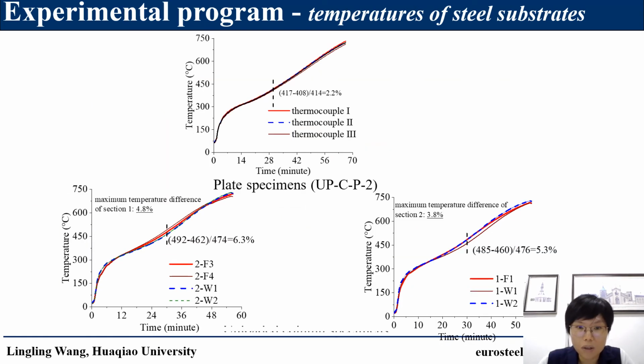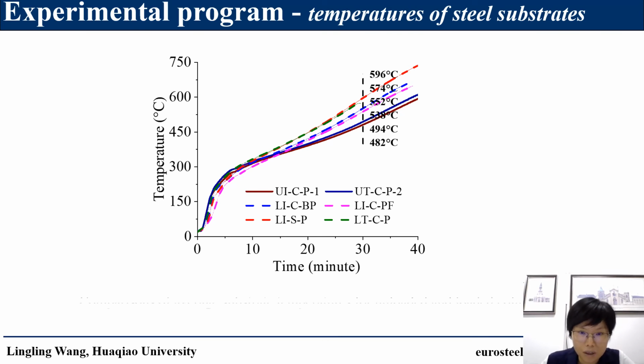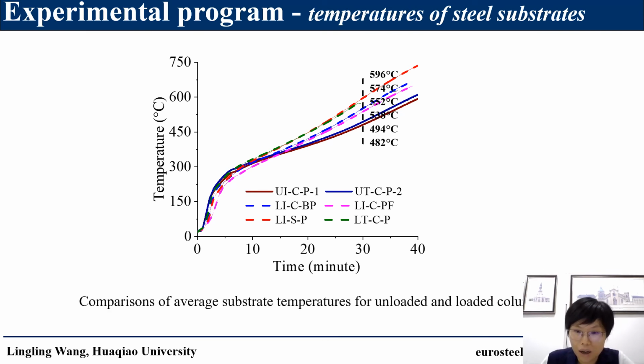For plate and unloaded column specimens, the maximum difference in steel temperature at 30 minutes of fire exposure is about 2.2% and 6.3% respectively. This suggests that unloaded specimens may be considered to have uniform temperature. This figure compares average temperature of unloaded and loaded column specimens where the maximum average temperature occurs. The unloaded and loaded column specimens had very similar section factors and the same intumescent coating data and were tested in the same furnace. Therefore, the observed large temperature differences can be attributed to the non-uniform intumescent coating behavior.